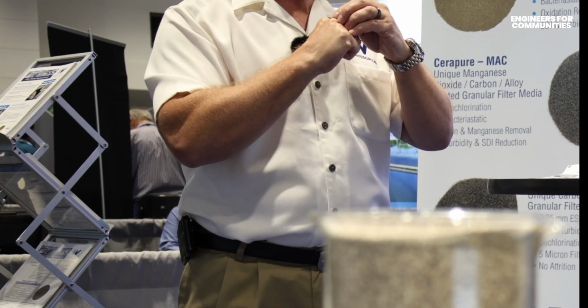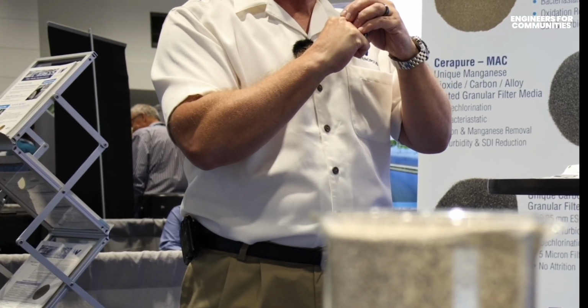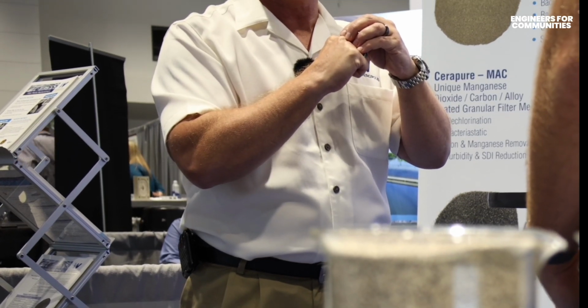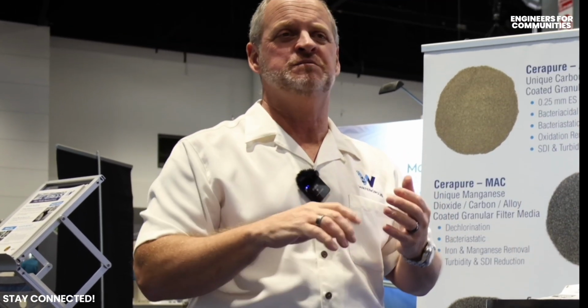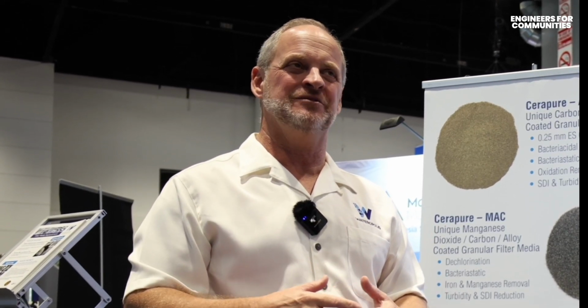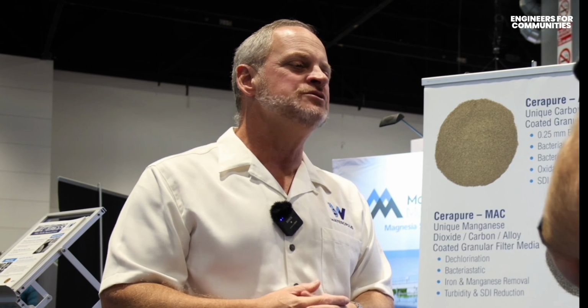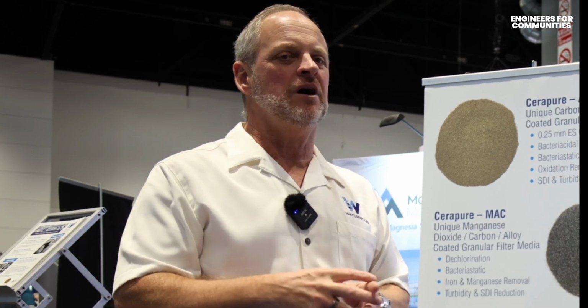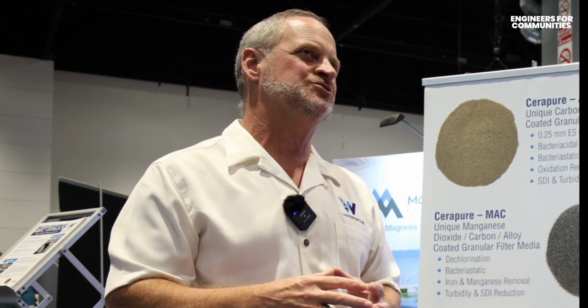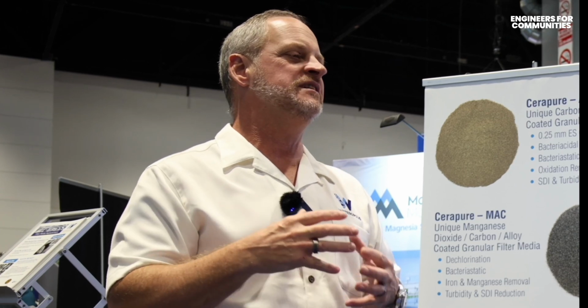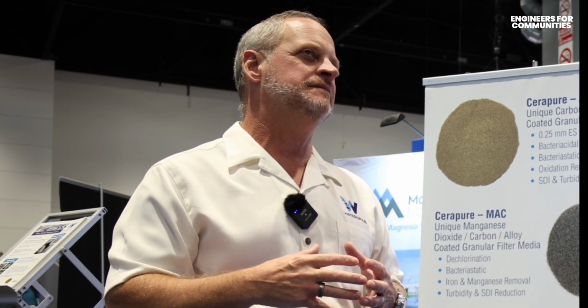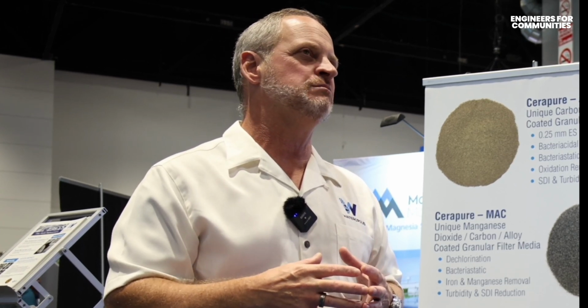There's no less than 16 different potential crystal structures that occur when manganese is oxidized. And that crystal structure is pH dependent, temperature dependent, time dependent. So it's not as simple as people put it out there to be. Does that mean there's 16 different ways to treat it, or do some get like 8 of those? No. Most removals are a little less fussy about which crystal structure it ends up being. I guess the point is that manganese is a complicated mineral and a complicated thing to remove sometimes.